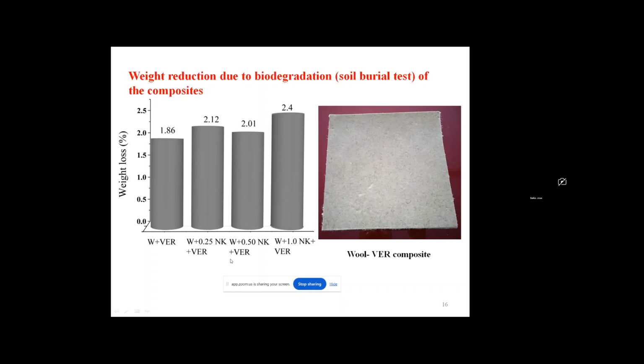the biodegradation is very minimal, even though the wool fiber is highly biodegradable in nature and it is a natural fiber. But the thick coating of vinyl ester resin is preventing the attack of microbes. As a result, we are getting a minimal amount of biodegradation. Weight loss is very minimal. At maximum it is 2.4% only.